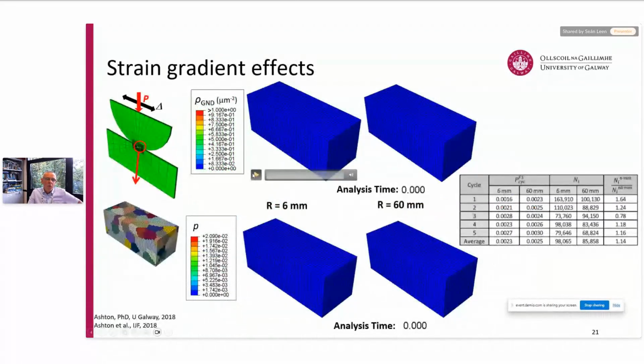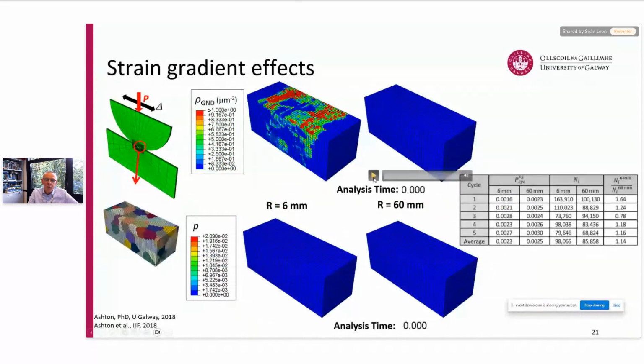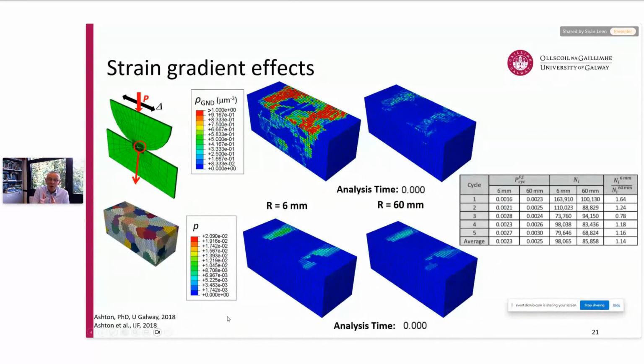And then I can hopefully run some simulations here which show how the geometrically necessary dislocation evolves. And the GND is a critical strain gradient parameter which can be measured and which controls the hardness of the material, essentially. And what we see is that it's not a very profound effect. It's reasonably subtle, but we do see that the smaller contact size has a significantly larger density of geometrically necessary dislocations, GNDs. The effect on the damage parameter P, which is this accumulated crystallographic slip, is more subtle, but we can see it is smaller.